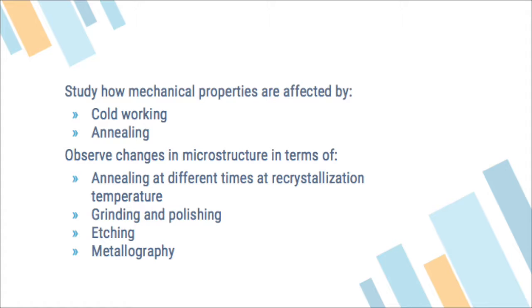And as we anneal at different times, we also perform grinding and polishing, etching, and do a metallography study on the sample. During grinding and polishing, we aim to achieve a mirror-like finish on the sample, so it's flat and clean. And during etching, we aim to expose features like grain boundaries, cracks, and uniformity on the sample. And later we'll do a metallography study by taking micrographs to identify features such as annealing twins, grain boundaries, and scratches.